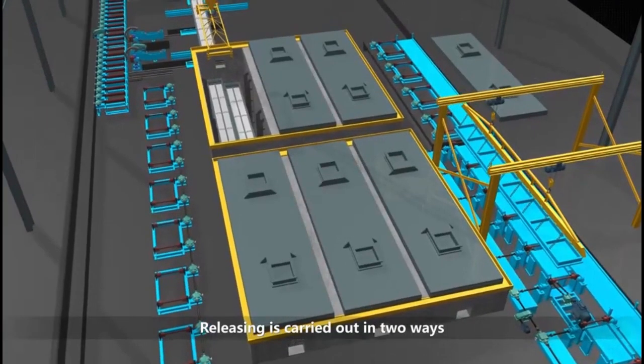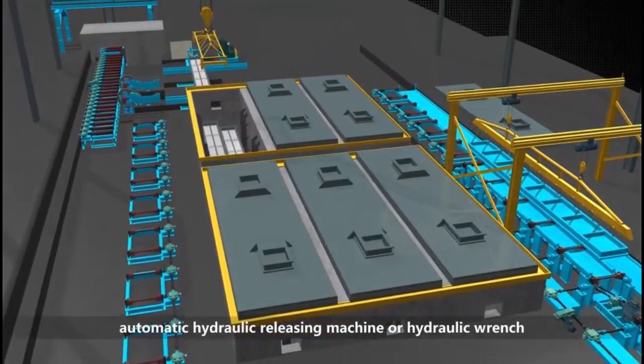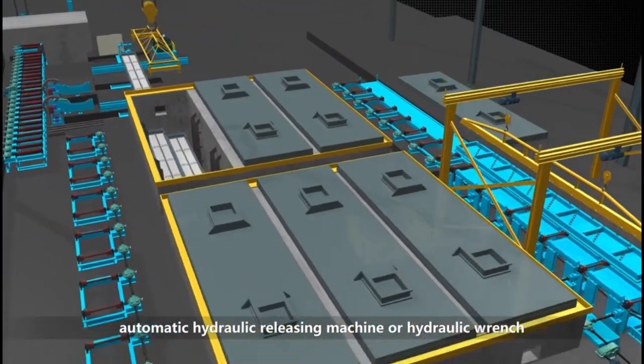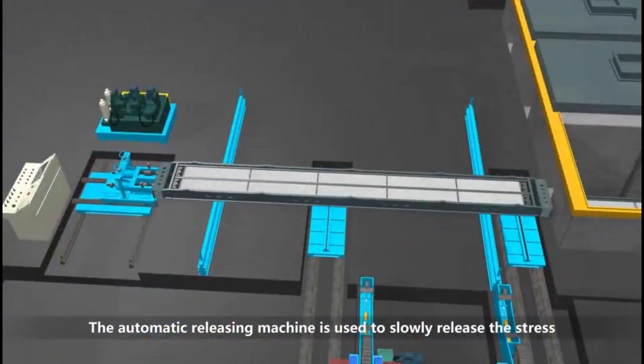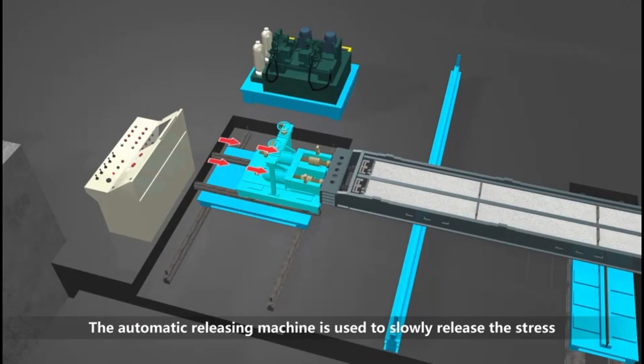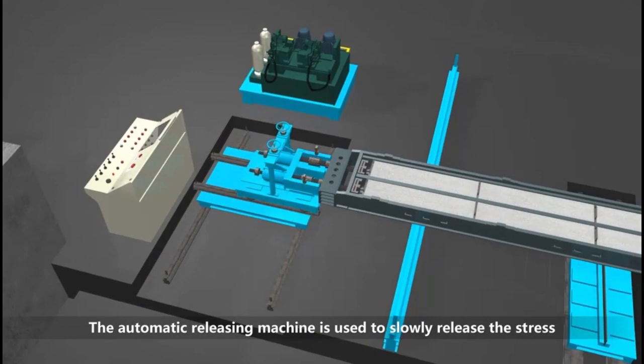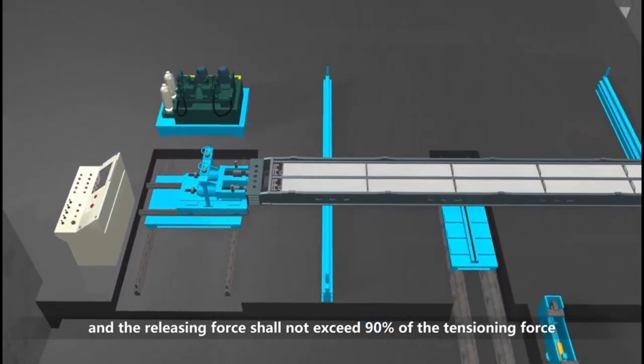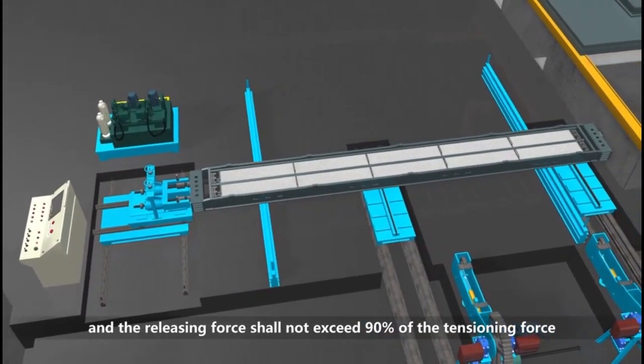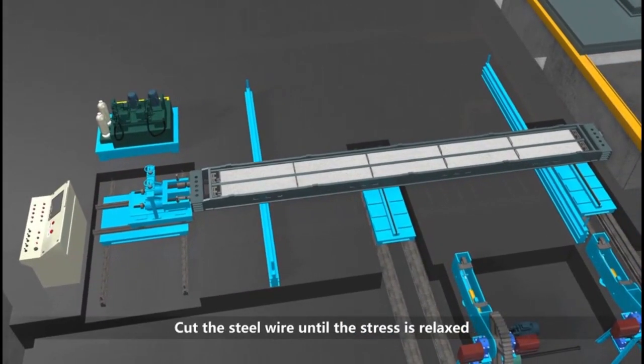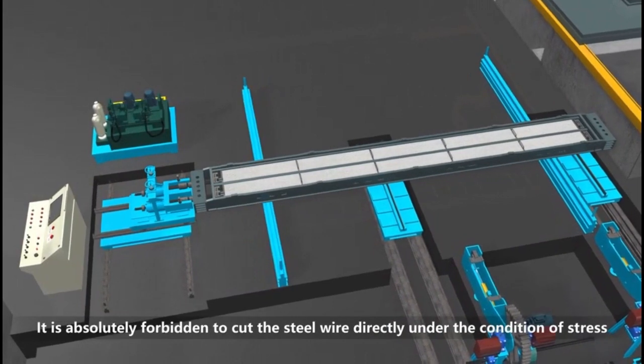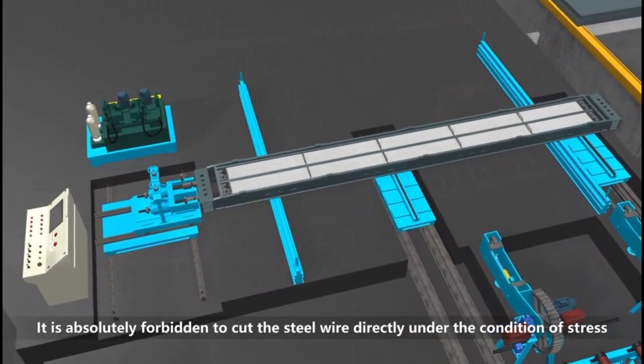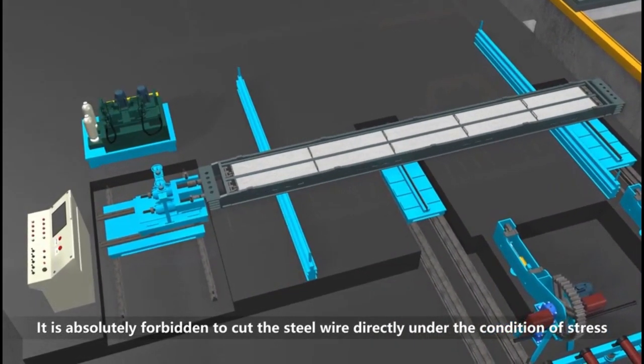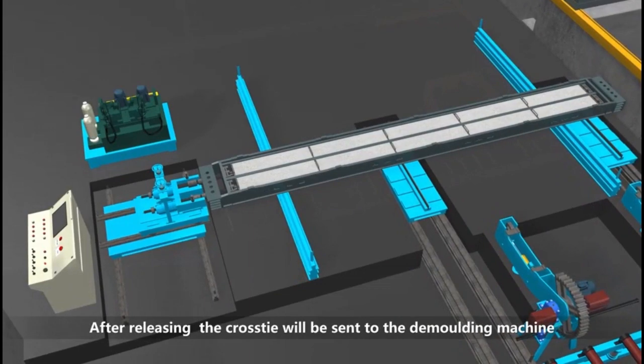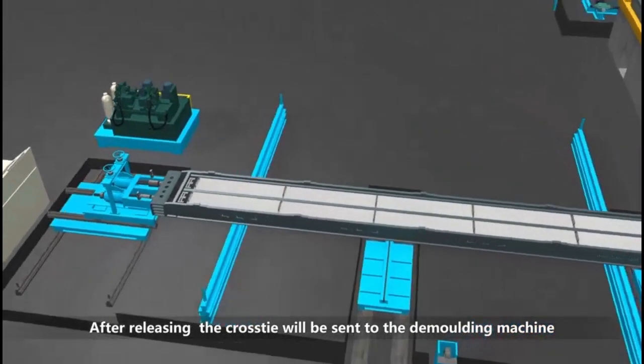Release process. Releasing is carried out in 2 ways: automatic hydraulic releasing machine or hydraulic wrench. The automatic releasing machine is used to slowly release the stress, and the releasing force shall not exceed 90% of the tensioning force. Cut the steel wire until the stress is relaxed. It is absolutely forbidden to cut a steel wire directly under the condition of stress. After releasing, the crosstie will be sent to the demolding machine.